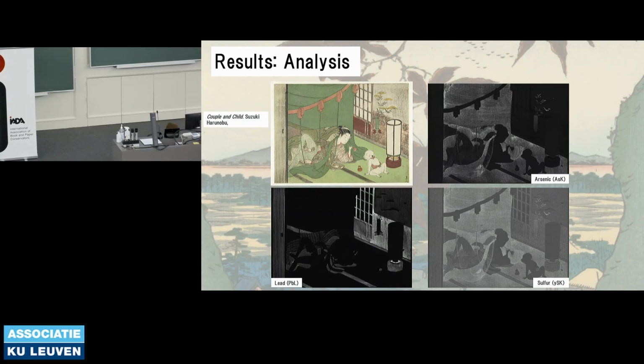For the analysis of the prints using macro XRF, it was found that red lead was apparent in all of the suspected areas of each print. In particular, red lead was found more commonly in architectural features, though it was also found in clothing, accessories, and landscapes. Sulfur was not detected in any of these areas, but this is likely a limitation of the analytical process. It was observed that a sulfur-containing pigment, orpiment, was apparent on 5 of the 9 prints examined, though it could not be determined if this had any effect on whether or not these prints discolored more or less.